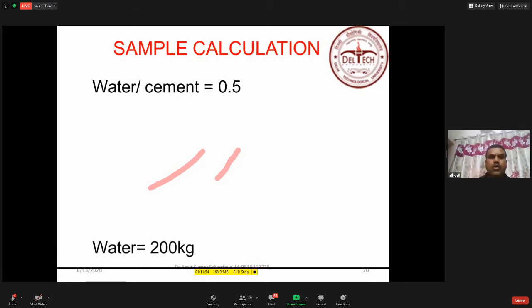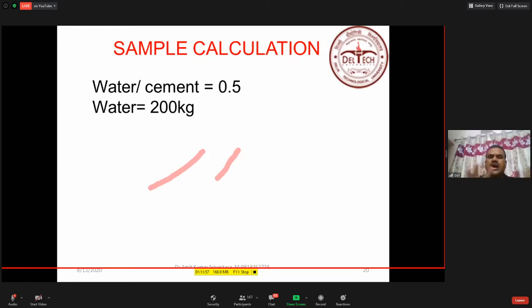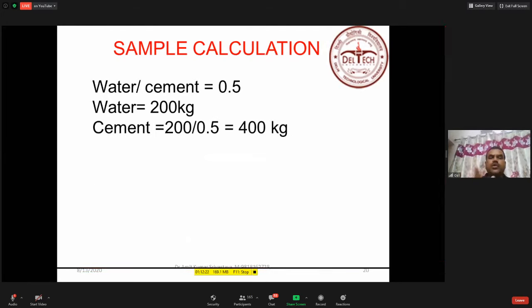So normally water required is 200 kg. I am just assuming. So it depends upon what is the slump, what is the flow, what you require. It may vary a little bit, but whatever the grade of the concrete you are going to manufacture, and for the same workability and for the same slump or for the same flow, you have to keep the water requirement as same or constant. So water requirement is 200 kg. So now if I say the water cement ratio is 0.5, then what is the cement I required? I will be requiring the cement of 400 kg.